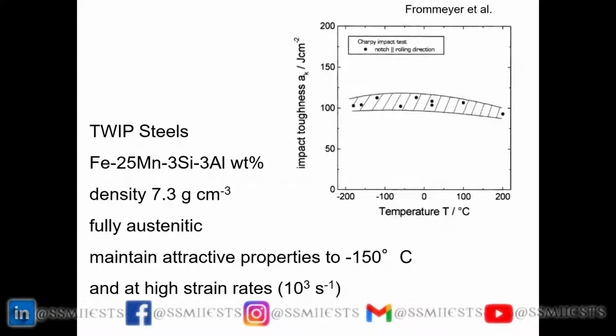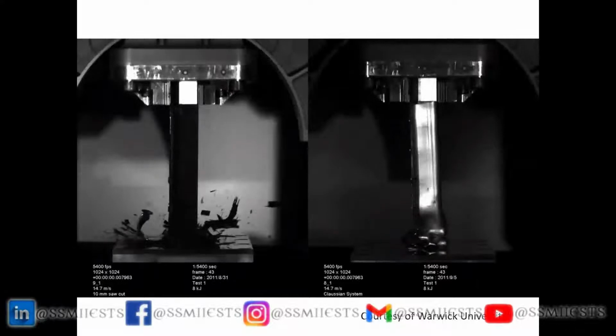So if you go to the next slide, this is a movie that I obtained from Warwick University. And what this is, you take a square-sectioned material. On the right-hand side, you have steel. On the left-hand side, you have composite. And do a crash test. So these are the sort of elements that go into cars, so that when you have a frontal impact, basically the deformation absorbs energy. On the left-hand side, when the composite fractures, it's because the interfaces are being broken, and that is the mechanism of energy absorption. On the right-hand side is plastic deformation. Go to the next slide.